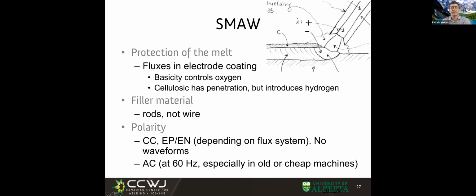So, much like everything that has fluxes, I mentioned this for subarc welding, but it's also true for flux core, and it's also true for stick welding. With the fluxes, we can have basic or acidic fluxes, right? And this basicity or acidity controls oxygen. Typically, the basic fluxes mean low oxygen. Acidic fluxes mean higher oxygen, but other advantages, for example, easier removal of the slag. Filler material in this case is rods, it is not a wire anymore.